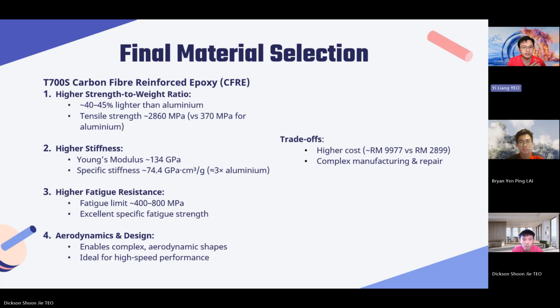Its higher strength to weight ratio compared to aluminium is around 40 to 45% lighter than aluminium. And also the tensile strength is 2,860 megapascal, which is greater than aluminium's 370 megapascal. So the greater the tensile strength, the better the material is. Moving on with the higher stiffness of carbon fiber reinforced epoxy, it has a Young's modulus of 134 gigapascal, and the specific stiffness of CFRE is around 74.4 gigapascal cubic centimeter per gram, which is 3 times better than aluminium.